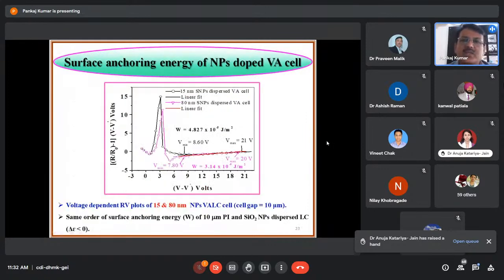But in case of the surface anchoring energy of nanoparticle VA cell, you can see the anchoring energy for 15 nanometer is W equal to 4.827 × 10^-5 joule per meter square. And for 80 nanometer, this is 3.14 × 10^-5 joule per meter square. So it is the same order of surface anchoring energy for 10 micrometer PI and SiO2 nanoparticle dispersible liquid crystals. It means that the anchoring energy is almost similar.